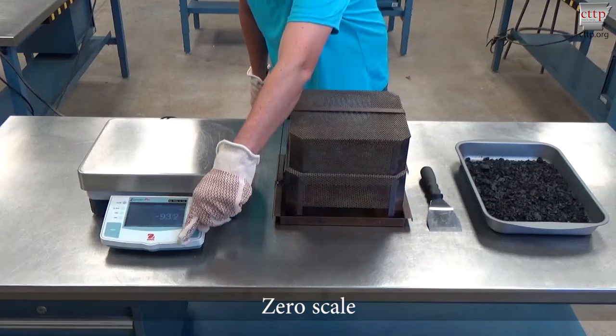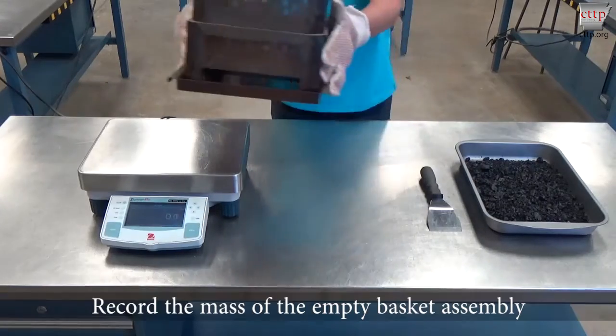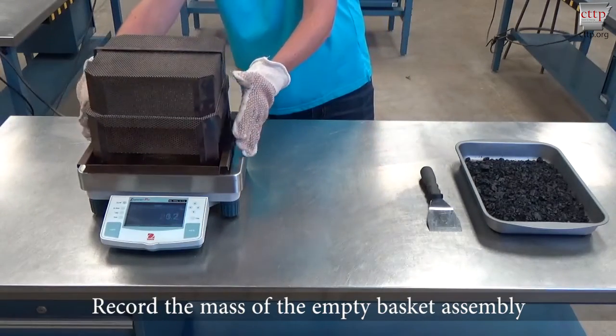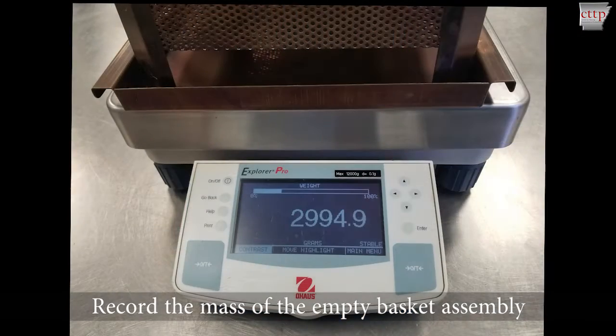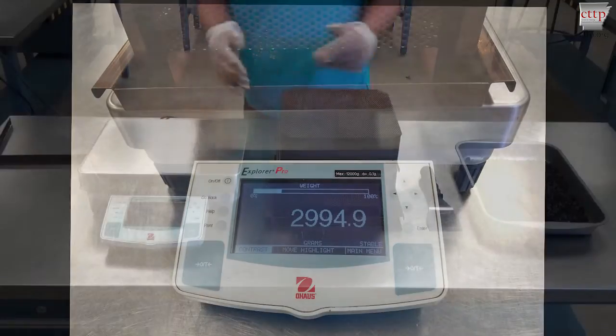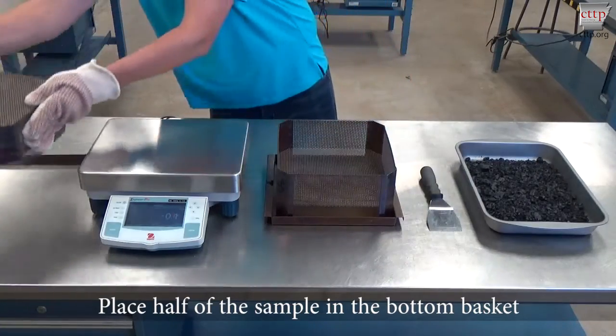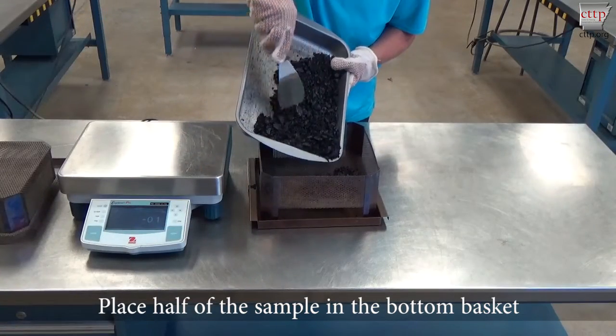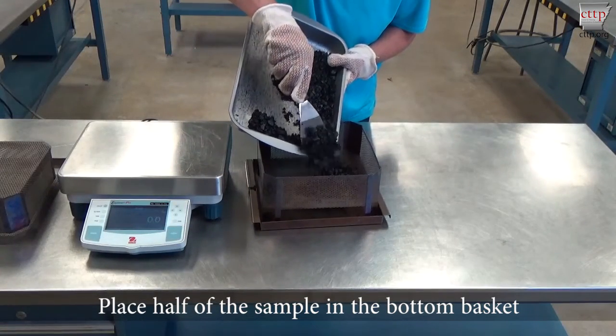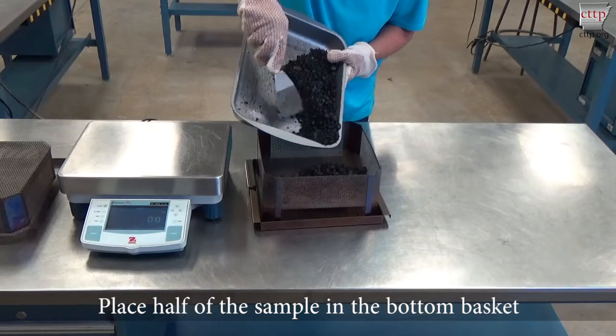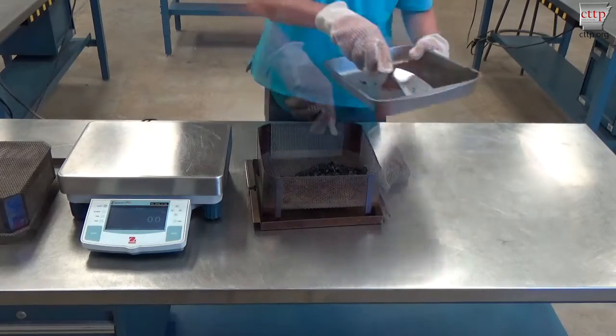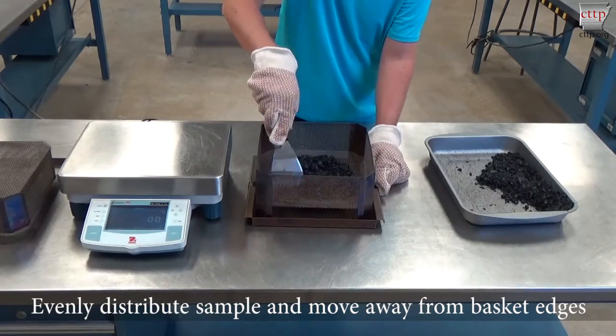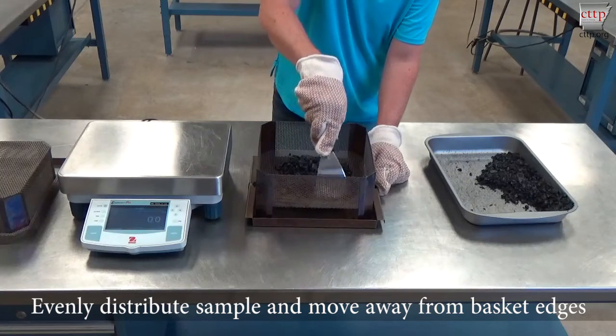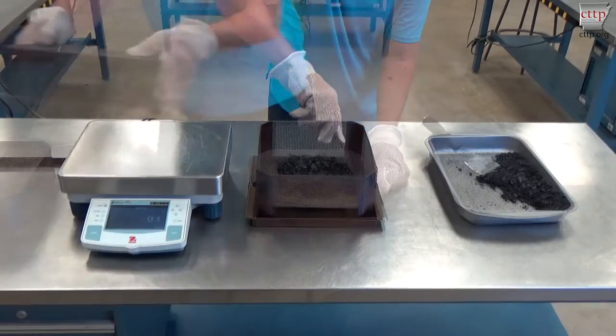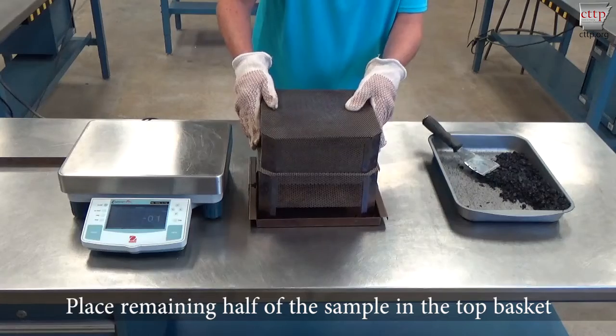Zero an external scale and place the basket assembly on the scale platform. Record the mass of the empty basket assembly, then remove it from the scale. Remove the top basket and set it aside. Place approximately half of the sample in the bottom basket. Evenly distribute the sample in the basket and move the mix away from the basket edges to prevent material loss during testing. Replace the top basket and remove the lid.